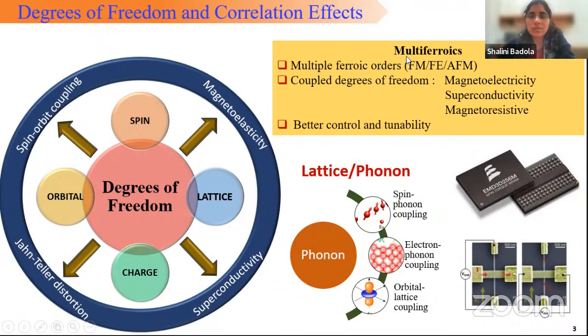The coupling between the fundamental degrees of freedom, which are spin, lattice, charge, and orbital, is important in the context of multiferroics because they generate competing many-body effects, which can lead to novel phenomena like magnetoelectricity, superconductivity, or magnetoresistivity. The coupling among these degrees of freedom has comparable energy scales, so any external perturbation to the system can play a decisive role in determining its ground state. Particularly for the lattice or phonon degree of freedom, any change or distortion in the lattice can modulate the electronic, magnetic, and orbital dynamics, and exploring them can be really important to get fundamental insights as well as potential applications. In today's talk, I'll be mostly discussing these coupling effects in perovskite materials.